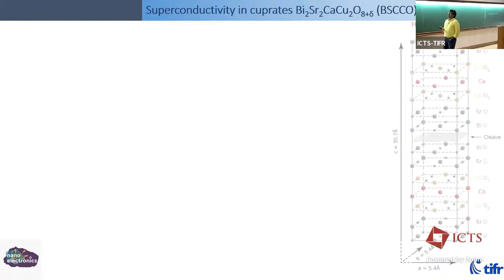Okay, so let me briefly talk about the material. I won't go into a whole lot of detail, but one of the van der Waals materials, which is not as much studied as graphene, is BSCCO. This is the acronym, but this is 2212, and it has a TC of about 85 Kelvin. It's a ceramic which has these planes of bismuth oxygen, strontium oxygen, calcium. Then the key is these copper oxygen planes, where the superconductivity lives. And there are these layers of other copper oxide planes, and they are Josephson coupled. There's an intrinsic Josephson junction because effectively these layers act like tunnel barriers. And superconductivity is strictly 2D and couples across the layers, and the TC of 1 or 2 unit cells is also the same as bulk.